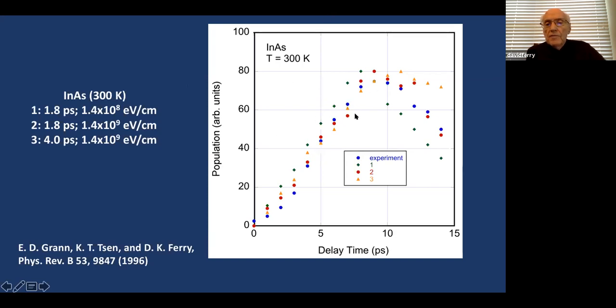So in order to match the experiment, the blue dots. And there's actually a blue dot under this red one, but it's exactly under it, so it's masked. So there's a peak here at about 8 picoseconds. And then there are 3 other curves for these conditions, done with ensemble Monte Carlo techniques. It's all reported in this paper 25 years ago. We need the phonon lifetime, and we need the coupling constant between the gamma valley and the L valley where the electrons are being stored. We can play with that since it's never been measured. We have an idea what it is.